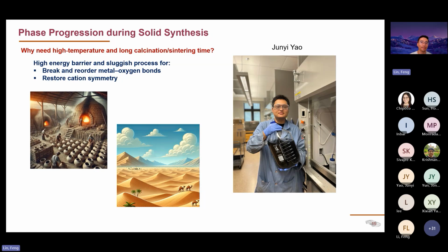And that's one unique aspect of battery cathode materials calcination: we have multiple factors in play. For example, in the typical sintering of ceramic, let's say aluminum oxide sintering, you don't get an oxidation state change. Aluminum stays as aluminum 3+. But the calcination of battery cathode active materials involves a lot of oxidation state change. For example, in nickel-rich layered cathodes, you have to oxidize nickel from 2+ to somewhere close to 3+, and that needs a lot of oxygen.